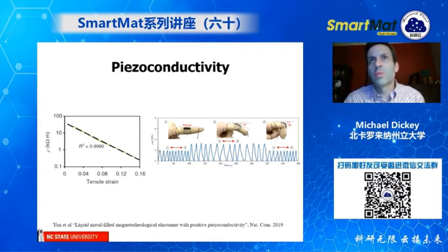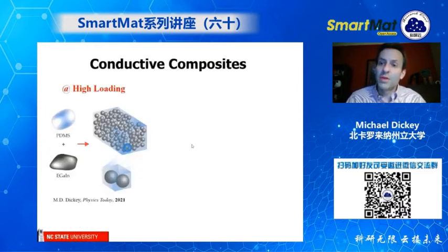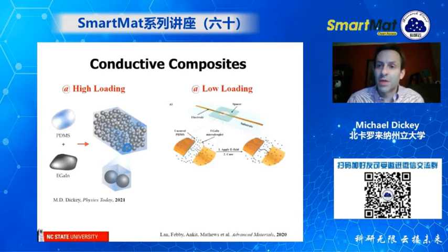And so what's remarkable about this is that this is on a log scale. So this goes up by 2 or 3 orders of magnitude due to this liquid metal structure. Now, these composites that I showed you, typically if you want to make them electrically conductive, you have to put a lot of liquid metal into the composite. So this is the silicone mixed with the liquid metal. And as you can see here, you have to put high loading, like 80, 90%, to really get all those liquid metals to become conductive. So we have this collaboration that shows that you can actually get around this and achieve conductivity at low loading.